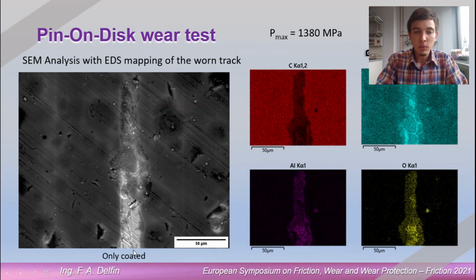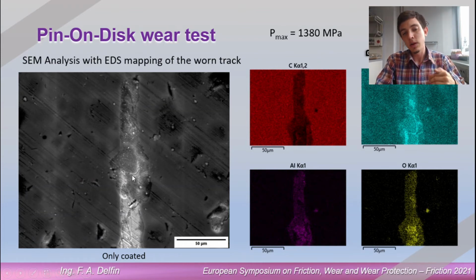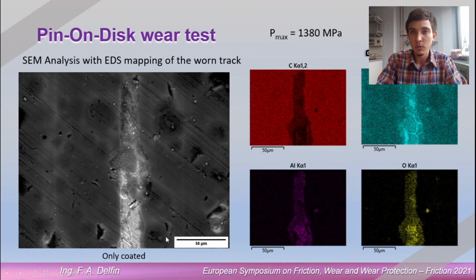But here, when we start losing the DLC because of the high Hertzian pressure, we start rubbing the ball against this chromium nitride or chromium carbide or chromium compounds. So it starts to wear exactly in this area, but not in the other areas around. So this is the problem with this poor adhesion of the coating.